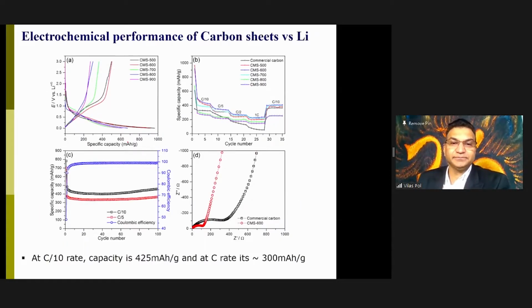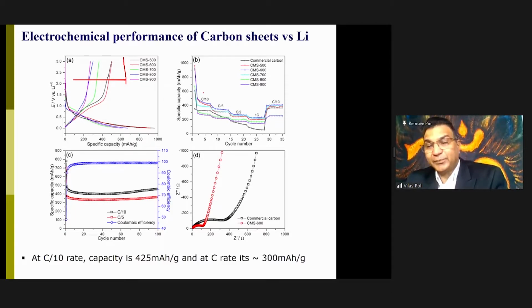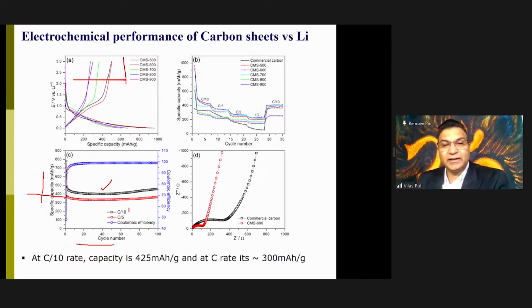That we use in our technology. Now, this might be too much for you, but I will simplify and let you know that this is battery performance. These are the different temperatures, 500 to 900 degrees Celsius, we utilize to make the carbonaceous material. And then you can see that the battery is charging and discharging very nicely. So this is the cycle number and this is the capacity. The typical capacity of graphite is 372 milliamp hour per gram. Actually, we are getting even higher capacity when your charging and discharging rate is slightly slower, up to 10 hours.